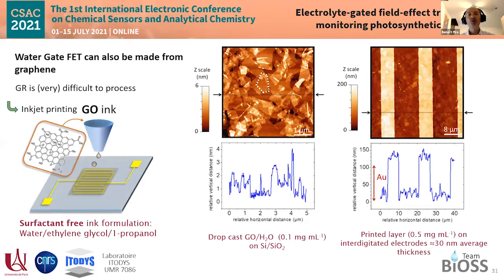I have 5 minutes, so I will continue on the fact that we also try to use, and we did actually, graphene to make such kind of electrolyte gated graphene field effect transistor to try to improve the stability, because if I say that organic semiconductors could be stable in water, it is true for some time. But if we would like to make the device very stable for a long time, several days or weeks, then at least for the moment, organic semiconductors are limited. So we switch to, or we try to use graphene.